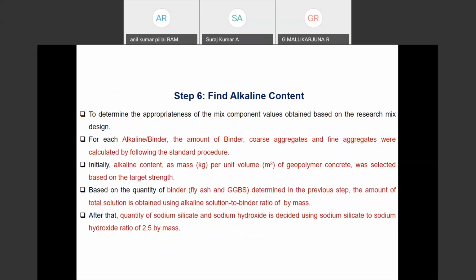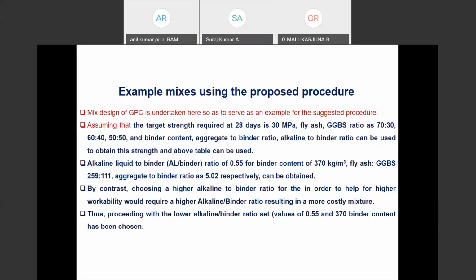That alkaline content you can get directly from alkaline to binder ratio also. Why? Because we know the binder content and we know the alkaline to binder ratio. And here the target required is 30 MPa. I had the choices of 70-30, 60-40, and 50-50. And the alkaline to binder ratio can be used for obtaining the strength.